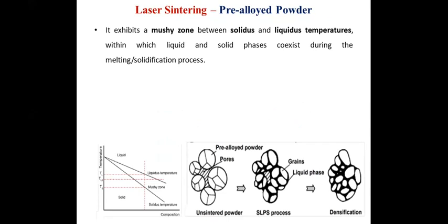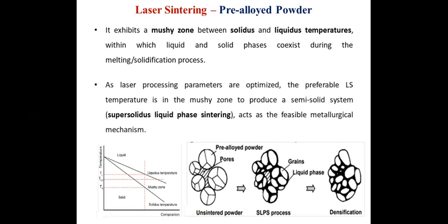It exhibits a mushy zone for pre-alloyed powders. Definitely there is a difference between the pre-alloyed powders, the multi-component powders and the pure powders when we are using them under the laser. There are solidus and liquidus temperatures you could identify here, within which liquid and solid phases coexist during the melting and solidification process. As laser processing parameters are optimized, the preferable laser sintering temperature is in the mushy zone to produce a semi-solid system, so that liquid phase sintering acts as the feasible metallurgical mechanism.